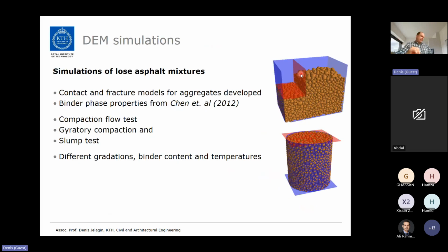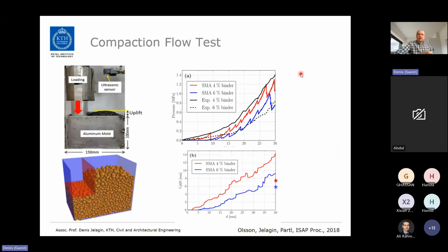Now, just to show some results from numerical simulations, we've done a few simulations in different studies looking at the compaction flow test, gyratory compaction, and slump test for different materials with different gradations. So the first example is from modeling the compaction flow test, and here we have black lines. They come from experiment for SMA with two different binder contents, 4 and 6%. And the red and blue lines come from numerical simulations with the discrete element method.